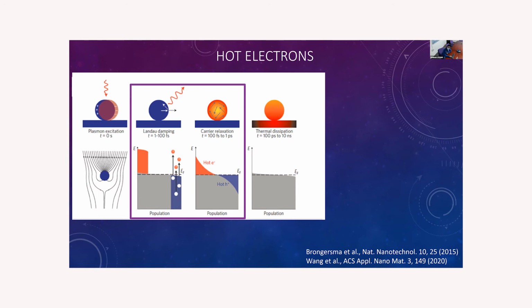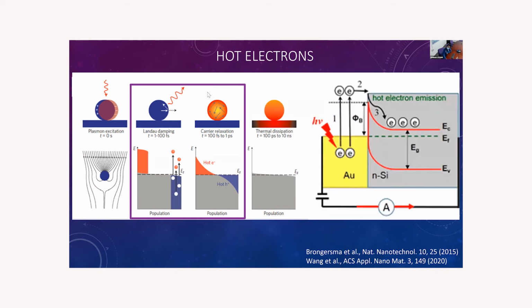For example, in our project, Plasmionico, we are working on this kind of system. We have a silicon substrate, some gold nanostructure on top of the silicon. What we want is to use these hot electrons in this very simplified 3 steps procedure. To generate the hot electrons, the hot electron should go to the interface between the metal and the semiconductor, and finally should enter into the semiconductor. In that way, you are using the energy that is accumulated in those hot electrons to produce currents, to use that for energy.